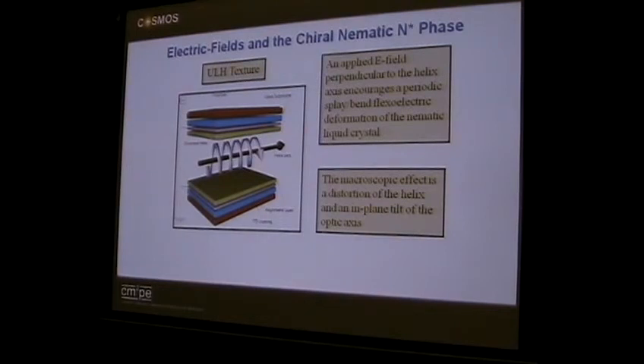The flexoelectric effect for a device puts the helix into the plane of the device. Okay, so you look down. If you look down through your system, you'd have a polarizer, substrate, alignment layers, indium tin oxide electrodes, and then the helix sits in plane. So you take your giant spring and you lay it horizontally. Okay, so your helix is sitting like that in the plane of the device. When you apply a voltage, the spring distorts. It twists over, or effectively twists over.